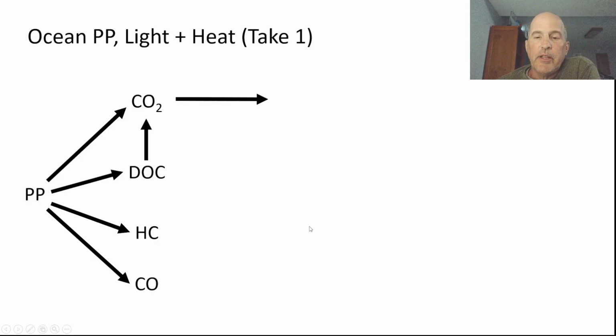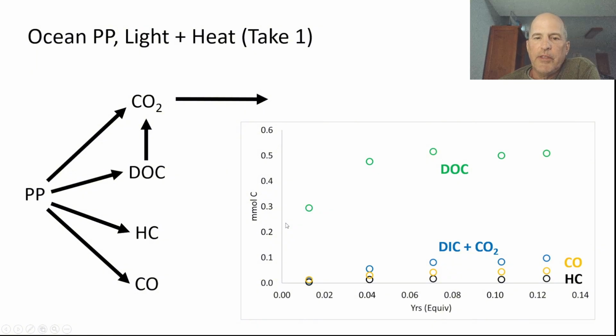So once I had all that data extracted, I was able to plot that in Excel. So the dissolved organic content, millimoles carbon is on the left. That allows you to look at everything on the same axis. So dissolved organic content comes up and then levels off. The dissolved inorganic content plus CO2, so that's basically CO2 in the gas and aqueous phases put together, also comes up and levels off. And then the CO and hydrocarbons just kind of come up slowly. But the error in those measurements, especially after my extraction process, is relatively high.